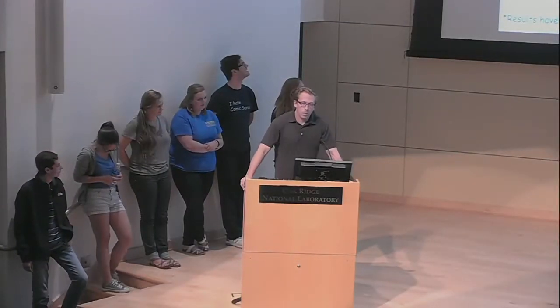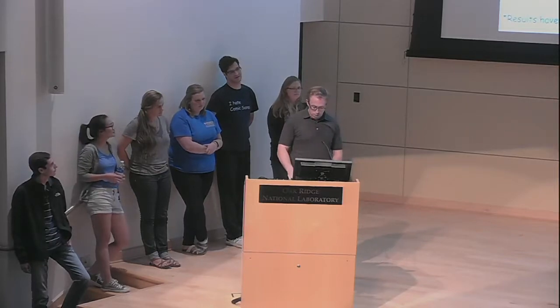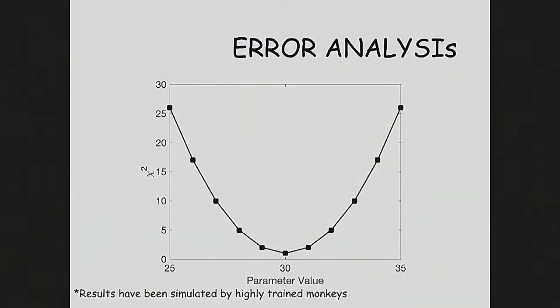All right, so we did this fitting using Igor and a module developed by the beamline scientists to help with this fitting. One of the things that beamline, or general scattering users, need to worry about when we look at our data and fit it with a model is error and error propagation. So during our discussion of this experiment, we talked about error analysis and when you can use just the covariances given to you from the fit. For the simple models, the Gaussian coil or the hard sphere, the error that the model gives you is adequate.